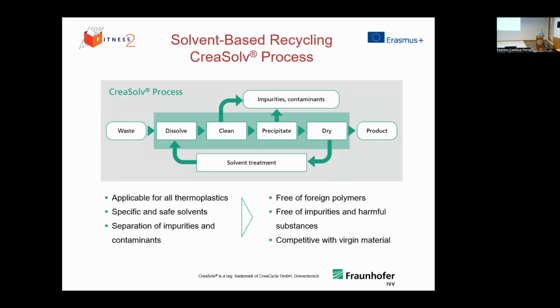And how does it work? When we have, for example, a waste, we can selectively extract the target polymer. So the target polymer goes into the solution and is fluid in this state. And then we can clean the solution and purify it from contaminants which are dissolved or undissolved. After that, we can precipitate the polymer and dry it to obtain a product which is free of foreign polymers and impurities and harmful substances and has qualities competitive to virgin material. During the drying, we also recover our solvent, which can be reused for the dissolution of the target polymer again. So the solvent is always used in a circle.